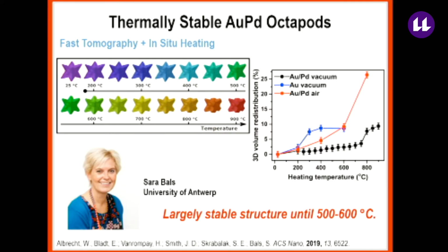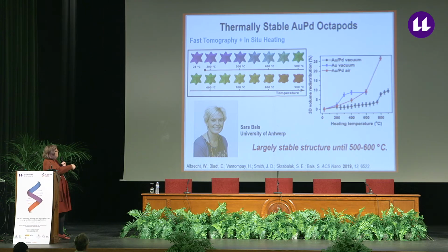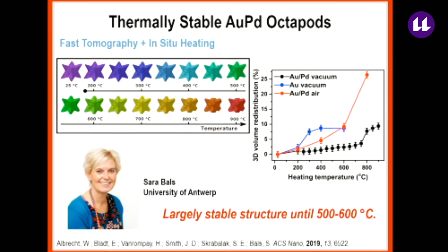And so shown here is the entire series that was collected by her students. And you can see very little change in morphology until quite high in temperature. Here's a plot of 3D volume redistribution as a function of heating temperature. The black line here corresponds to our gold palladium nanocrystals within the electron microscope. And it's quite stable with very little volume redistribution until around 600 or so degrees.